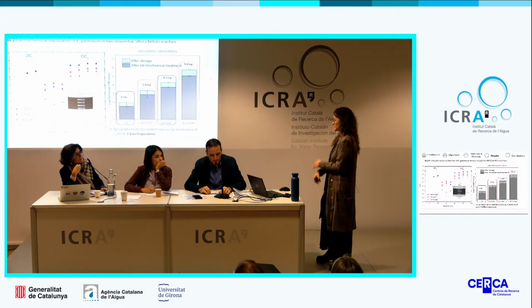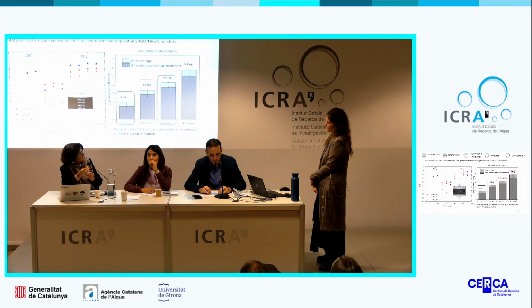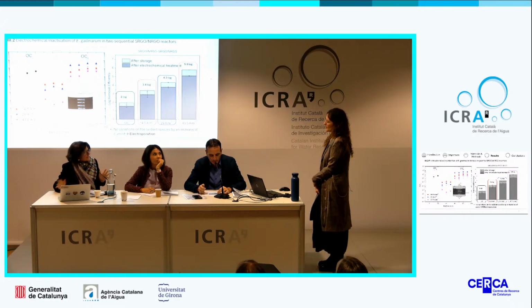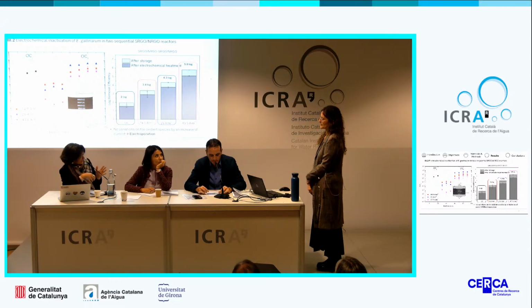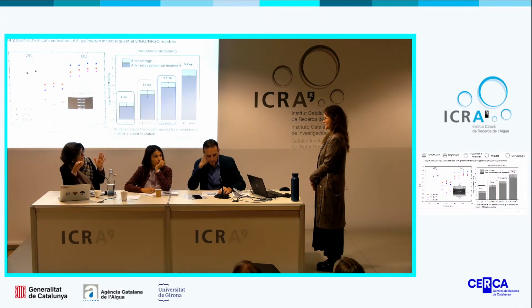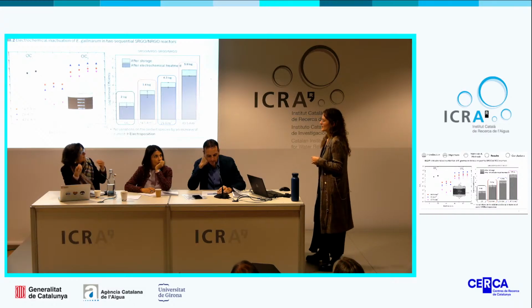Okay. Because for me, bubbles are a mechanical effect. So I didn't understand why, when the compounds are adsorbed, the oxidation is lesser, whereas for sulfamethoxazole it's better. Can you repeat, please, because I didn't get your point. The bubbles disturb the oxidation because of mechanical activity, yes, totally. There is no contact between electrodes or hydroxyl radicals and the compounds. Why can sulfamethoxazole, which is not adsorbed at the electrodes, go to the electrodes to be oxidized in a better way than the other antibiotics?